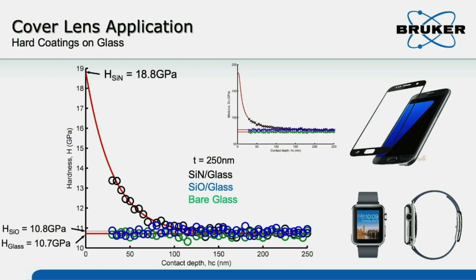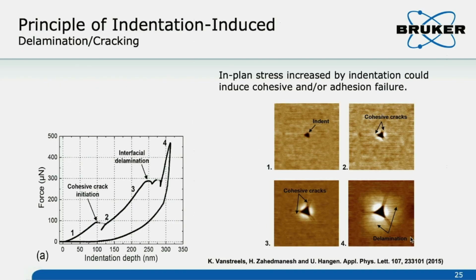So if we cannot get shallow enough indents, sometimes we need to use a model to do the fitting. So this red line is the model to fit the silicon nitride hardness, right? So you need a model. But before you apply the model, you still need the raw data of the depth profile, right? So this is for the ultra thin film measurement.